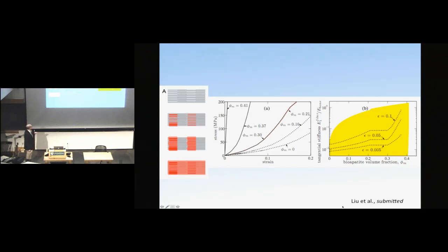We see very mild stiffening for mineral up to 21% as the gap channels are filled. Then almost no stiffening at all strain levels as the mineral grows over the mineralized gap regions. And then subsequently, the stiffness shoots up rapidly to the stiffness of bone as the mineral grows to form a continuous sheath over the entire collagen fibril.